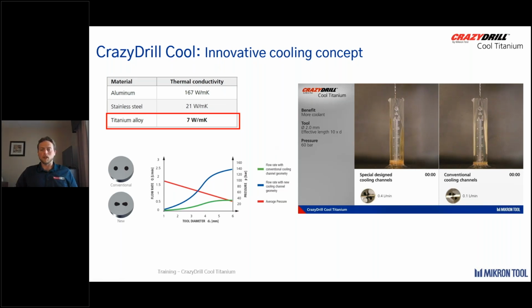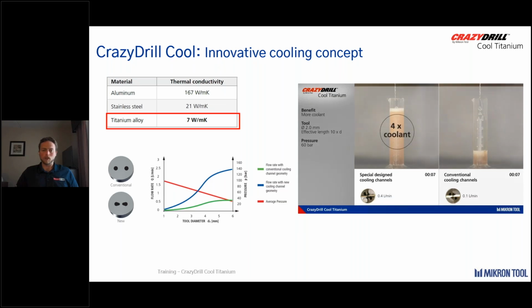I show this video to many people and they always think that I'm speeding one up. I promise you this is not the case. This is an actual live-time perception of the coolant channels in a real world environment, about 60 bar. So we can figure a little under 1,000 PSI coolant there, right? What this means is we're transferring about 4 times the amount of coolant to the cutting edge. This means we're able to maintain the cutting geometry better by maintaining a lower temperature at the tool itself.